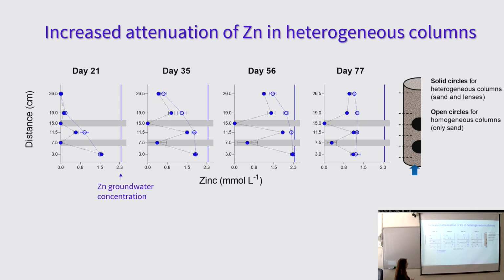The blue vertical line is showing you the concentration of zinc in the incoming groundwater. Based on that, we can see that we have accumulation of zinc in both the homogeneous and heterogeneous columns. But the accumulation or the retention of zinc is more substantial in the heterogeneous columns with those solid symbols, and that can be attributed to the presence of the lenses. But you can also see that the levels of aqueous phase zinc are negligible in the lenses themselves.